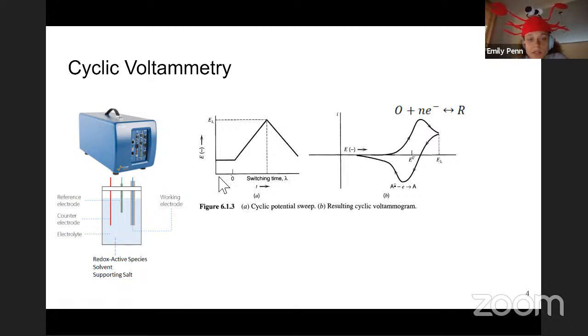For CV, what we're doing is we are modulating the potential over a time period, and we're recording the current. So here we have time on the x-axis, and the potential on the y-axis. You can see that as we increase the time, we're first increasing the potential, and then at some switching point, we reverse the potential and decrease it back to the original value. And then when we do this, we measure the current.